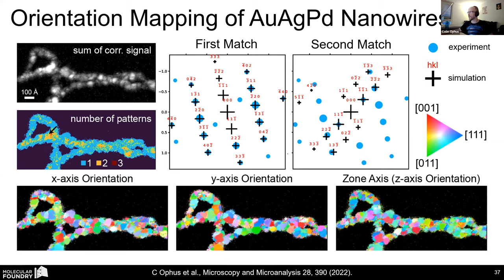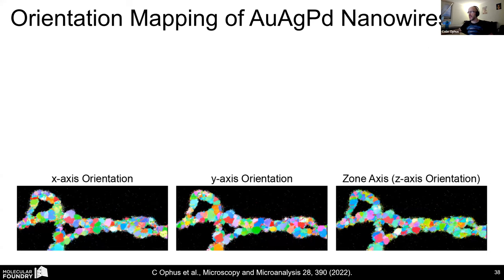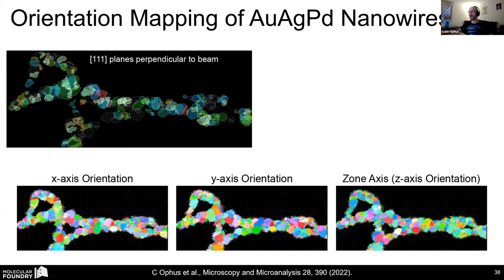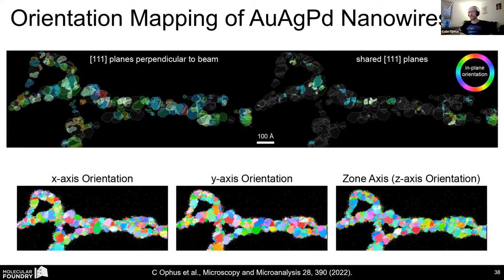And this is just showing the results for this sample here. You can see the many, many different nucleated polycrystalline grains in the helical nanowire structure. I have a couple of slides showing the 111 planes that are perpendicular to the beam, but even more interestingly, the shared 111 planes between adjacent grains. One of the hypothesized formation mechanisms for this material is twinning along 111 planes, which leads to this helical structure. And we found a statistically significant number of these shared 111 planes. The next step in this experiment would be to tilt the sample and repeat at many different tilt projections to try to get a full 3D orientation map of all of the grains here.